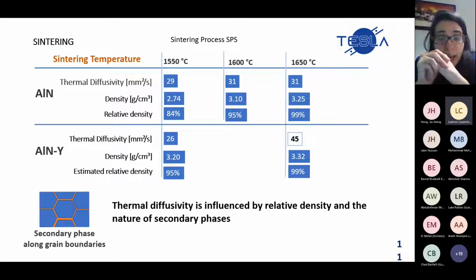what I want to show is how it affects one of the processing factors in sintering, which is the sintering temperature, with two types of materials: aluminum nitride and aluminum nitride doped with yttria. We did the sintering at three levels of temperature, reaching different relative densities, which impacts not much, but a little bit. It will influence the density of the material, and it will also impact the thermal diffusivity of the material. The greater the thermal diffusivity, the greater the thermal conduction of the material. If you include a little bit of additive, you enhance the thermal diffusivity of the material.